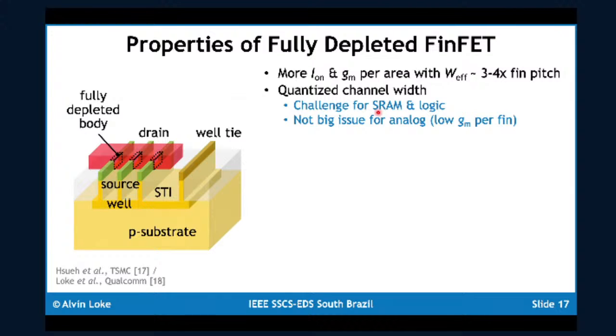For logic, this is also a bit of a problem. It's not as big an issue for analog circuits because the overdrives are actually quite low, and you're not getting a lot of GM per fin, typically no more than on the order of 10 to 100 microsiemens per fin. When you're working with millisiemens kind of GMs, you obviously need multiple fins at minimum.